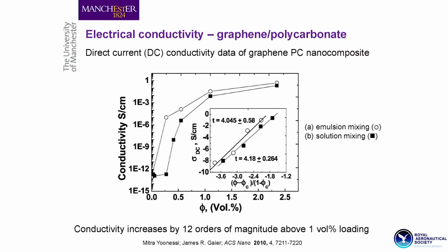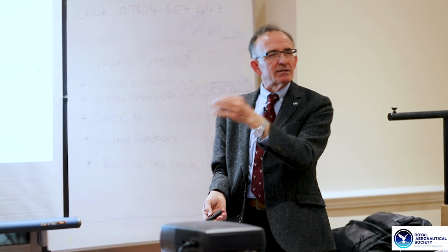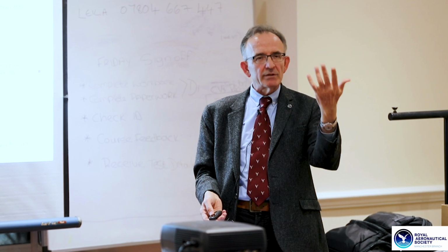So you characterize it, and then you measure electrical properties, and we can see conductivity. Conductivity increases by 12 orders of magnitude. So you have a polymer which is not electrically conductive, and suddenly, with a small amount of graphene, it conducts electricity.